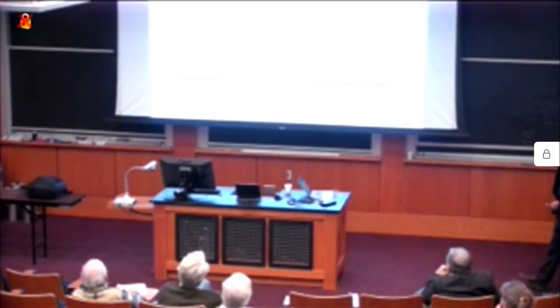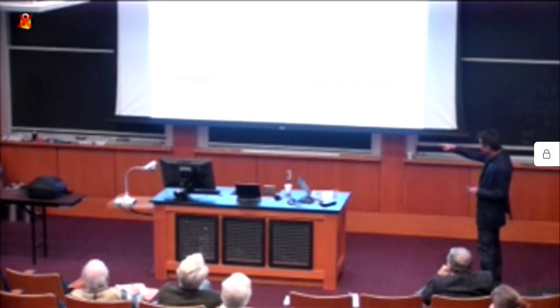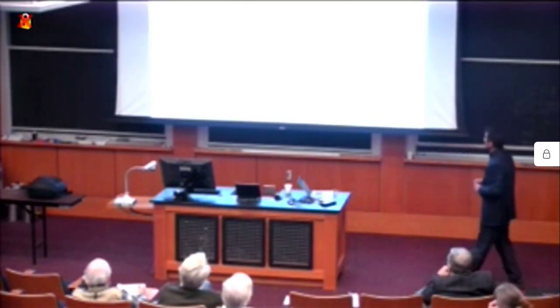But again, there are these very fascinating, at least for our community, underappreciated and underutilized techniques that can really create very different structures than conventionally synthesized. So there's a few efforts over the last few decades that developed ways to, for example, do exactly this Jenga process. You can literally imagine there was a column of oxygen here, pull that out. Another column of oxygen. So you can actually transform stable known materials that we can easily grow in both bulk and thin film form, and we can stabilize something that might look like an analog to the parent compound of cuprates. So indeed, Danfeng Li was able to do this.